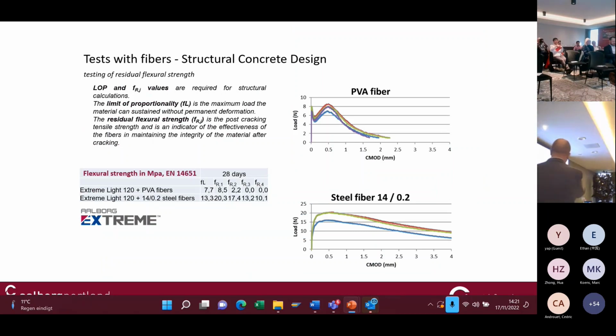We also did a lot of tests of fibers, of course, steel fibers, PVA fibers, and important for us is also the residual flexural strength we can obtain. But of course, we see that we can lift it up even to 13 MPa, 14 MPa. Flexural LOP, that is the limit of proportionality, and then going up for residual strength, that is the straining behavior. So we can even go higher until 20 MPa, but of course later this afternoon the people from the fibers will go more into detail.